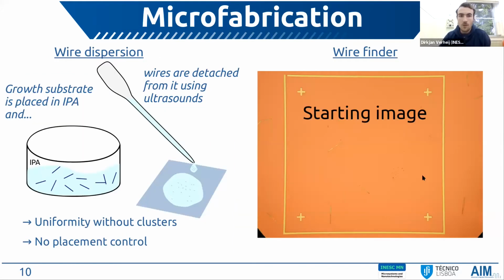So like I said, I wanted to highlight a specific part of the microfabrication process involving the alignment process. And this has to do with the wire dispersion and how we perform this step. So to put the wires on the device substrates, we put a small piece of the original growth substrate in IPA and apply some ultrasounds to it to detach the wires from the growth substrate. And this creates this suspension of microwires inside the IPA. And then we basically just put some droplets on the device substrate. We wait until the IPA evaporates. And this results in a nicely uniform dispersion of the microwires, without clusters.